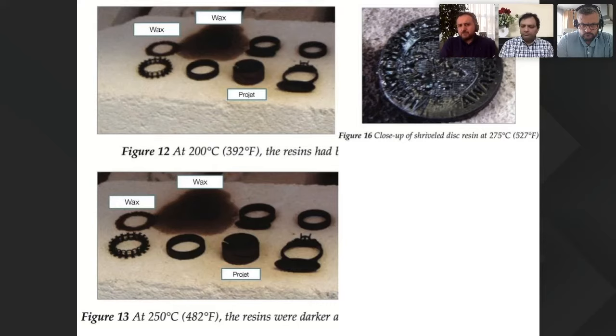And if you look at some parts, some pieces, at 275 degrees in those resins, you already see that there are some deformations happening in the resin. This can be due to expansion or change in the shape of the resin.